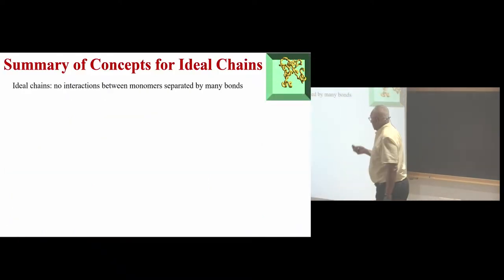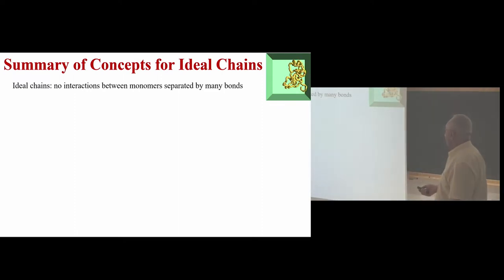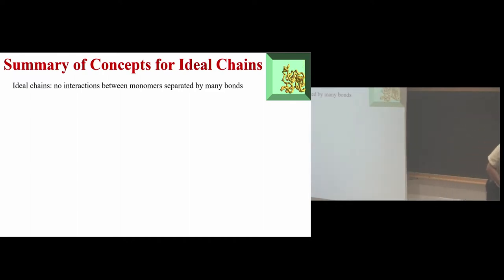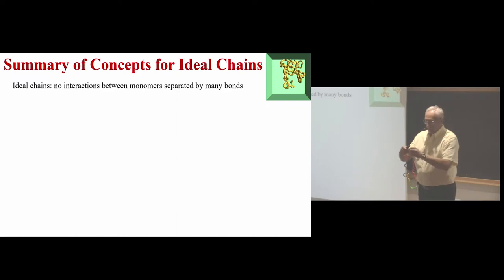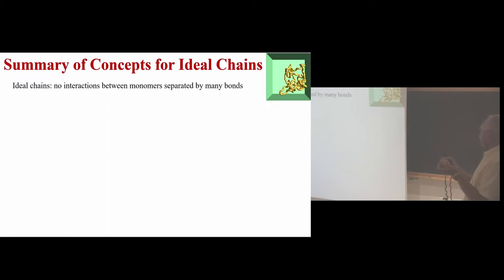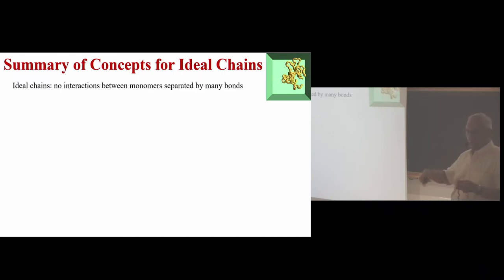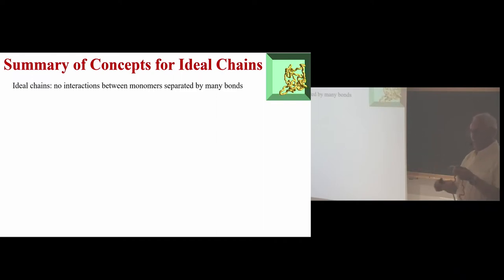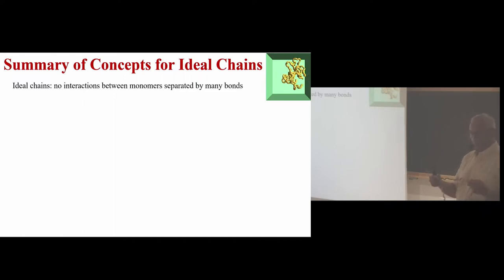Summary from the previous lecture. What you learned is the ideal chain. I have a sample of this type of freely jointed chain — this is a ring, we're going to break it so it's a chain with ends. When two sections come close together, we assume there's no interaction between sections that are far away. It still assumes some interaction between nearby sections — that's how you get differences like C-infinity corrections due to stiffness — but far away monomers completely ignore interactions. That's what ideal chains are.